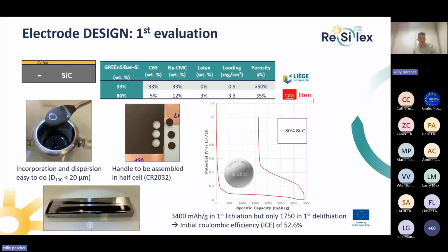I show you here the first evaluation we did. Compared to the electrode formulation that was used by Hamid, here we started with already 80% of silicon carbon composite, limiting the inactive components to less than 20%. We also increased the loading, and we densified the electrodes to have something more representative.